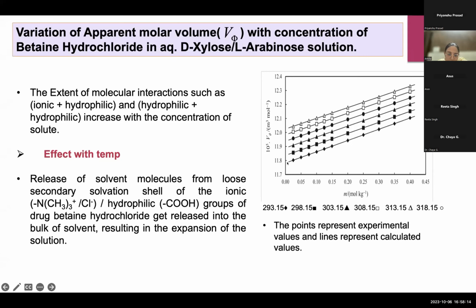What we found through this graph was that as the concentration of the carbohydrate solution increases, the apparent molar volume was also found to increase. With respect to temperature also, these values were found to rise. The reason is that as the temperature increased, the solvent molecules present in the loose solvation shell of the ionic and hydrophilic groups of the drug betaine hydrochloride got released into the bulk of the solvent, which resulted in the expansion of the solution. So the molar volume increased with the rise of temperature, and that is reflected in the graphs.